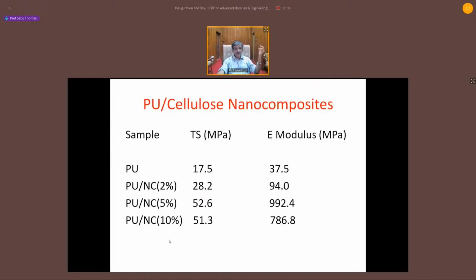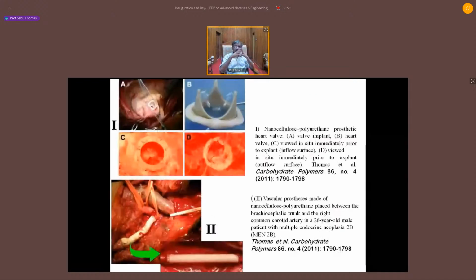We introduced nanocellulose in the polyurethane. Look at the quantum jump we got. 37.5 became 992.4 megapascal, the modulus. So he was really interested in this data. You know, ultimately what we did with the Brazilian corporation, the Brazilian hospital, they did lots of animal studies, and eventually they made nanocellulose polyurethane prosthetic heart valve. And we published a series of papers.